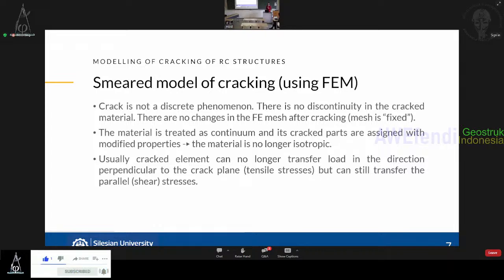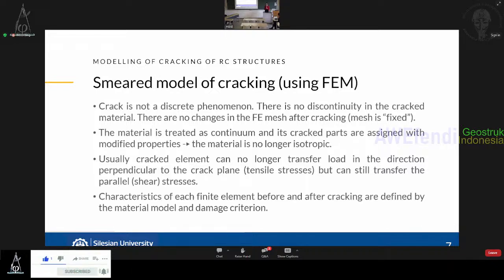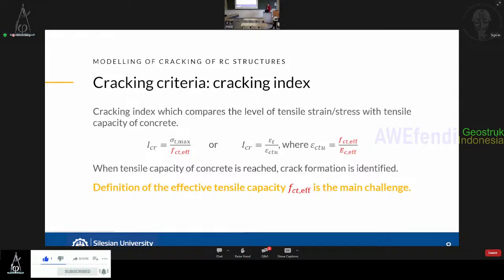And we assume that in such a cracked element, this element can still transfer some residual stresses, but these are parallel or shear stresses, while the tensile stresses can no longer be transferred by the element. So the characteristics of such an element, which is partly healthy and partly cracked, are defined according to the applied material model and damage criterion, which I would like to now discuss in a little bit more detail. So first of all, we need to define that the crack potentially appeared in an analyzed element.